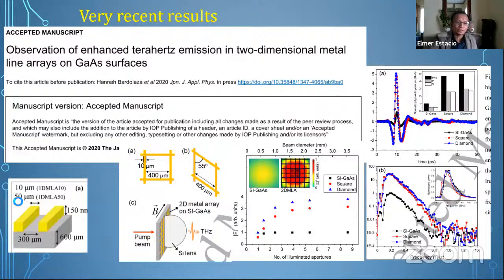And lastly, we went back to the work on trying to look at how terahertz photons can interact with very, very constricted spaces and result in terahertz generation amplification. This was in 2014 in Optics Letters. And very recently, we were able to show that if instead of a 1D array of metals, we use a 2D structure, then we can generate spherically or circularly polarized terahertz radiation, in 2 dimensions, not just in 1 dimension. And we were able to show that we can increase the terahertz radiation even up to 2 orders of magnitude in power. This is terahertz radiation spectra for the bare gallium arsenide, and these are for the surfaces wherein we deposited 2-dimensional metal arrays. So actually, this has not come out yet.